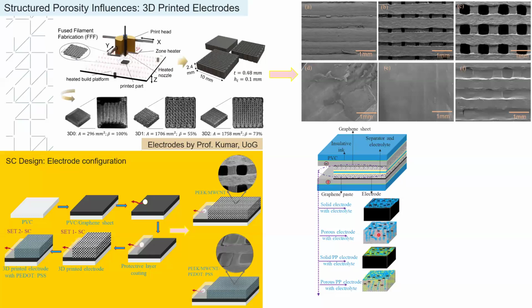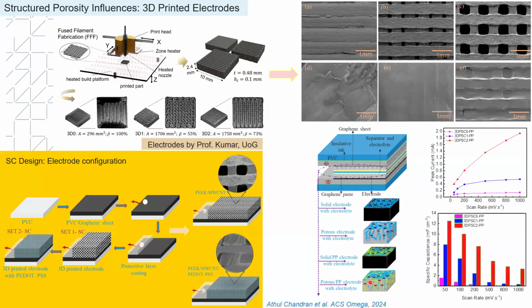And once we have a conductive polymer on there, depending on the conductive polymer, the electrode is further reacting with these conductive polymers and also in the porous structure. So the conductive polymer, when we drop it on this 3D printed electrode, will diffuse inside the 3D structure and enhance the active surface area. Once we compared this, we noticed that the large pores with a more oriented structure with the conductive polymer show better current acquiring by CV analysis, and it shows a very high capacitance in the device performance as well.